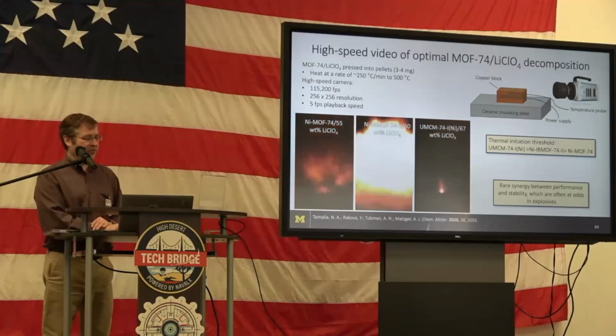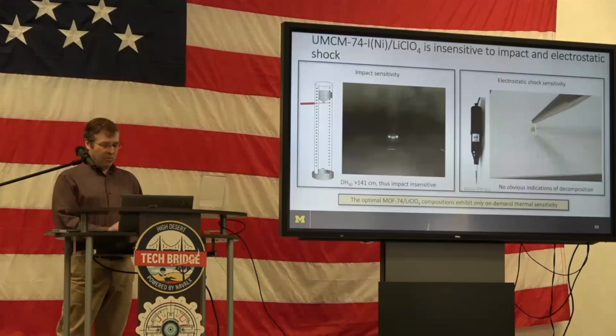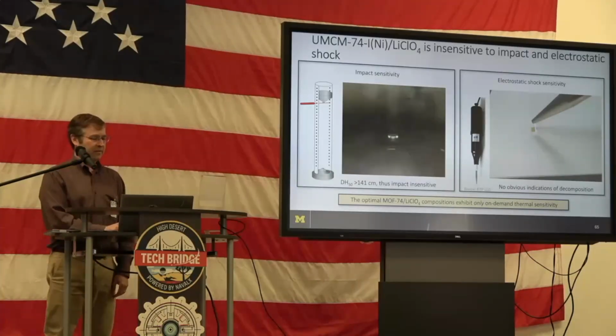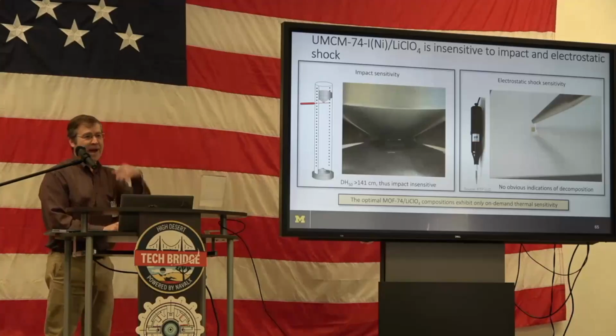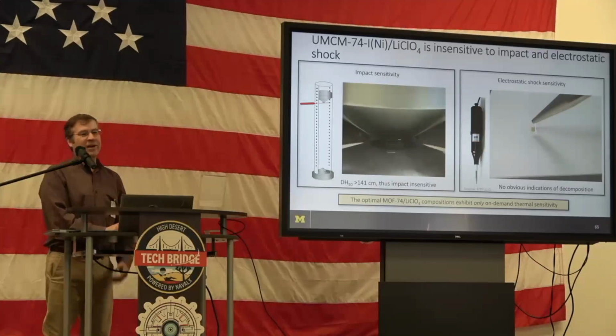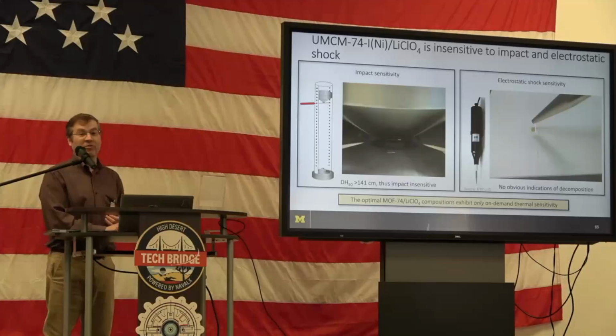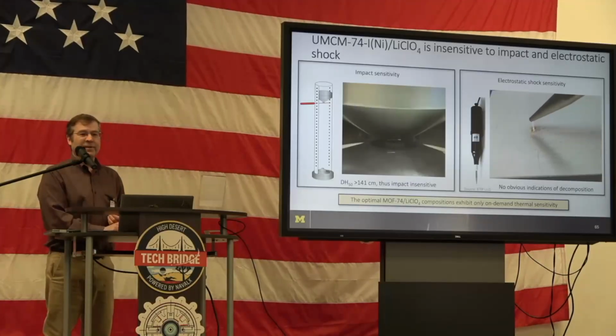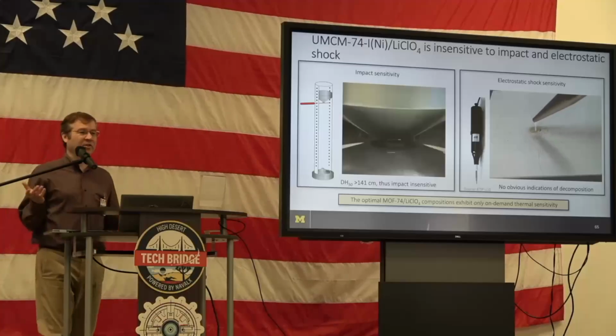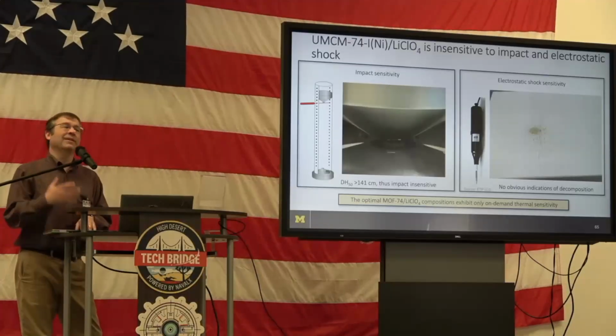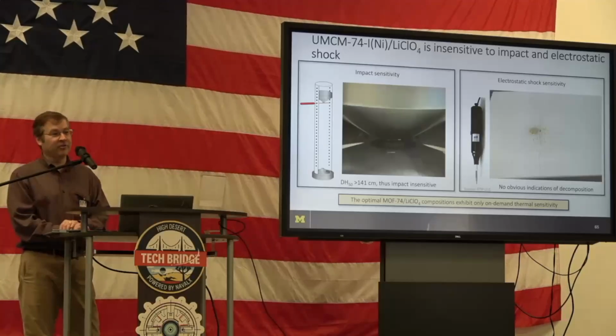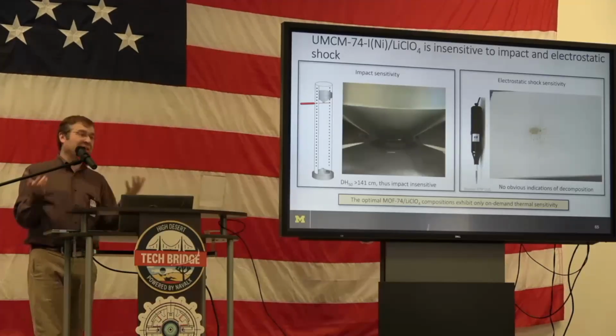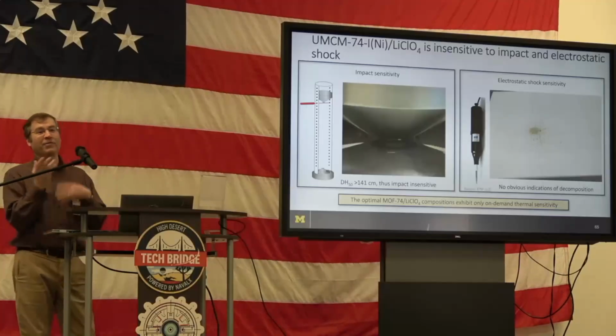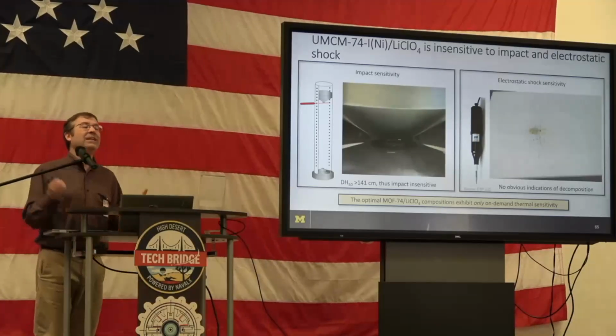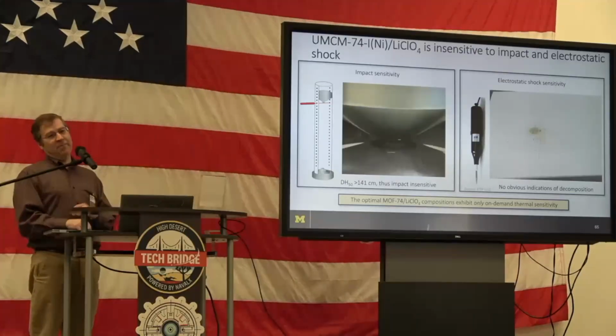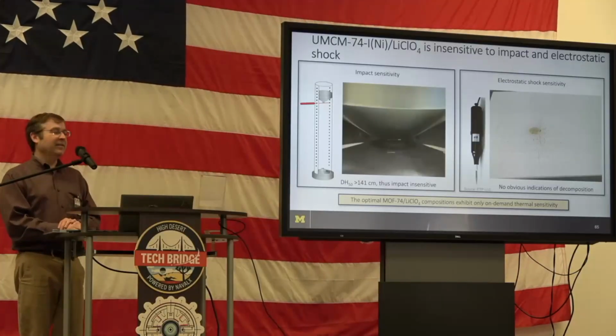Okay, so what about other measures of sensitivity? Well, we can do drop impact, and we use the maximum height of our apparatus. It doesn't go off. We don't have one of these fancy electrostatic dischargers, but we have a Tesla coil. So the composite's totally insensitive to impact and to electrostatic discharge. And this is because that mixing is on the sort of 25, 50 micron level until you melt this stuff and you get that melt infiltration. And then things become very sensitive.